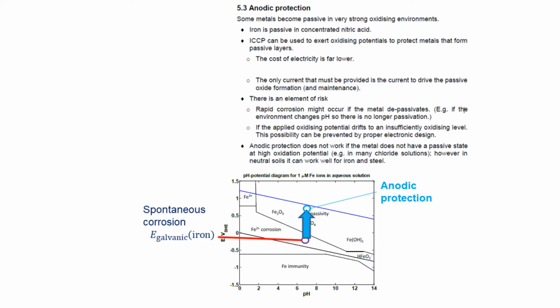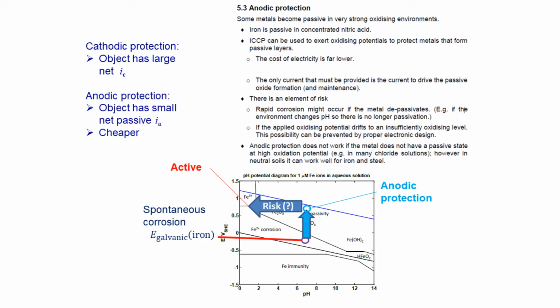We have the useful observation that when we looked at the pH potential diagram for iron, we saw that it was one of the metals which actually becomes passive in a very strong oxidizing environment. Iron, for example, is passive in concentrated nitric acid. That's potentially a risky thing to do, to store concentrated nitric acid inside iron containers, but it could potentially be done because the iron should remain passive against corrosion in the strongly oxidizing acid.